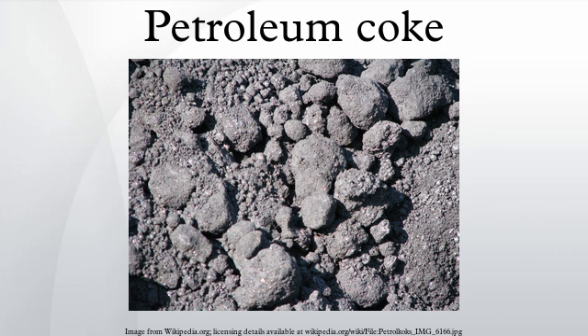Petroleum coke is over 90% carbon and emits 5 to 10% more carbon dioxide than coal on a per unit of energy basis when it is burned. As petroleum coke has a higher energy content, it emits between 30 and 80% more CO2 than coal per unit of weight. The difference between coal and coke in CO2 production per unit energy produced depends upon the moisture in the coal and volatile hydrocarbon in coal and coke.